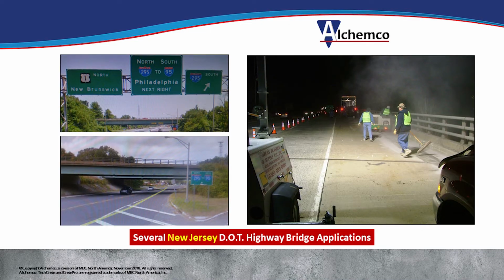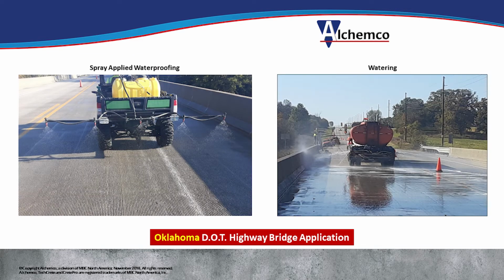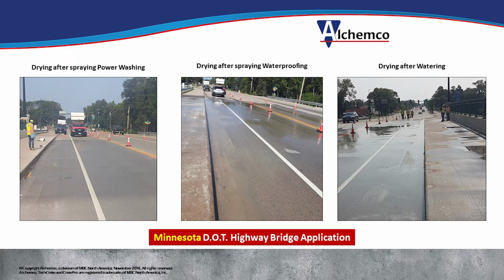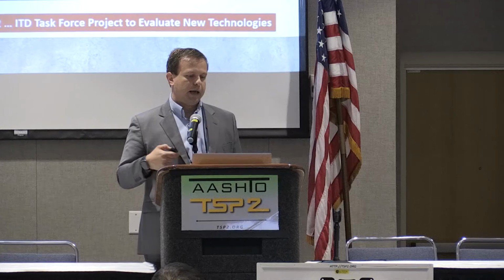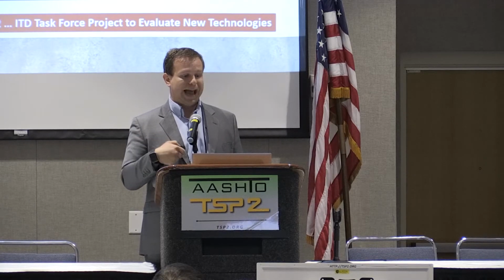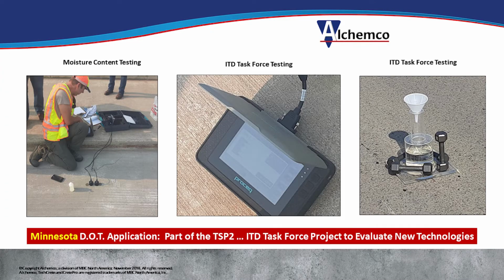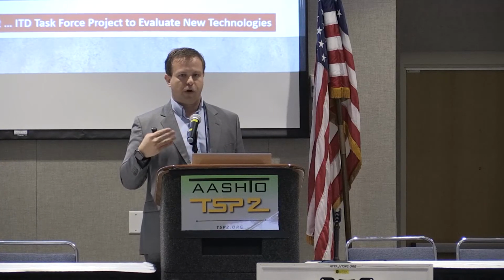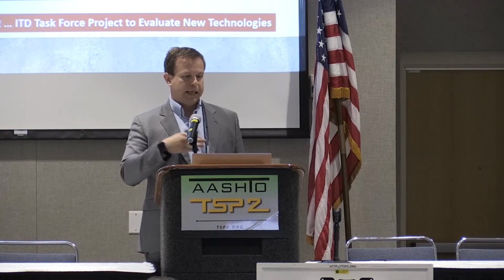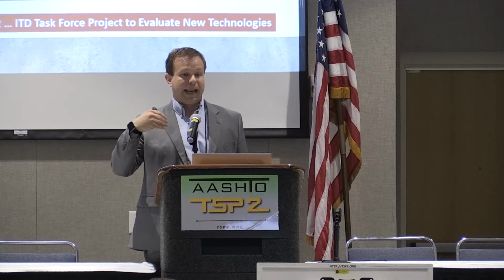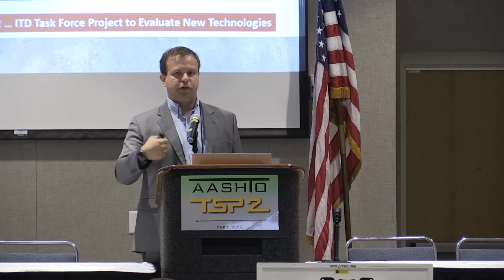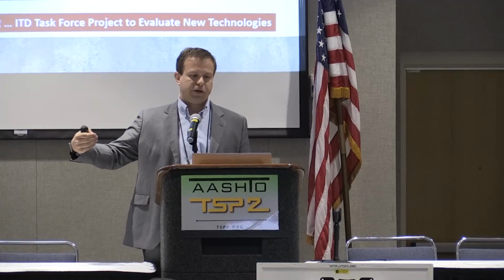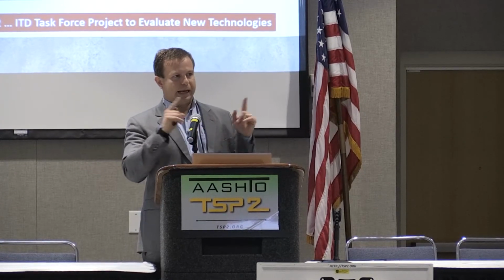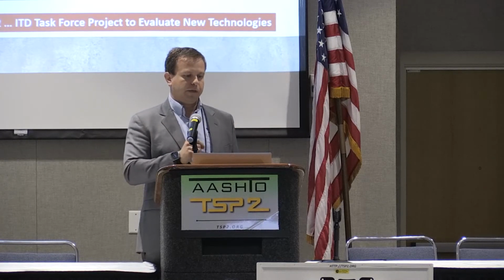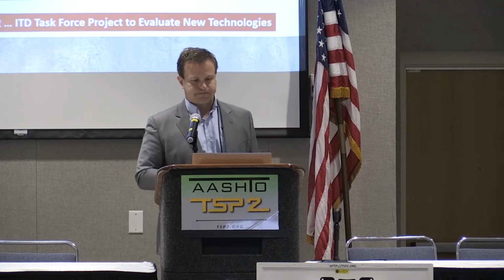Here we have New Jersey DOT, Oklahoma, Minnesota. Minnesota, this is one of the pictures from the report that we did for the ITD, where they measured the water penetration on the concrete and the water penetration when there were cracks. They also measured the chloride ion before the application. And for the ITD program, the next test is going to be 1 year after the application, and then 3 years, 5 years, and then 10 years after the application, exactly to be able to show the benefits of the long-term results of this technology.